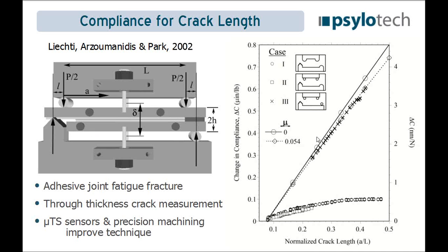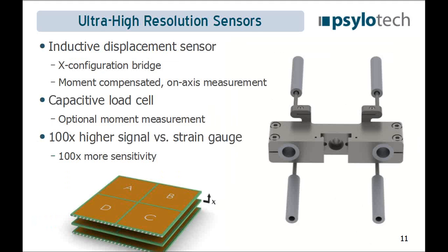So higher resolution sensors allow for better resolution of the compliance. So let me talk a little bit about the sensors themselves and the instrument so you can get an idea of how we accomplish this. Essentially, the displacement sensor is an inductive voltage divider. You can see on the right here, there are four inductive coils located strategically such that the average location is in the center. So we're actually measuring the displacement on axis.